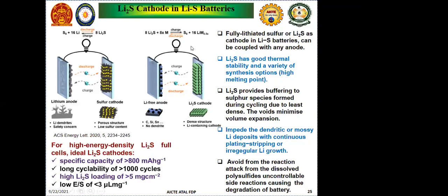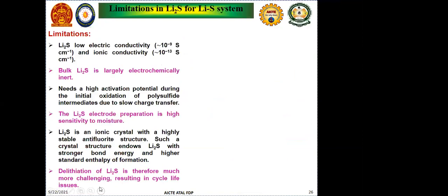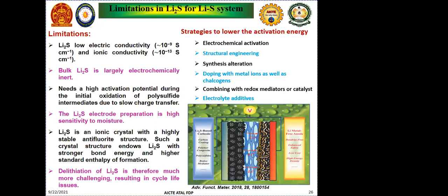We have to adjust the electrolyte as well as electrode material, so that the sulfur loading will be sufficient for the system. Especially for better battery performance, like a specific capacity around 800, and the cycling stability, we want around 1000. So we have to keep a high loading of Li2S, more than 5 mg per cm square for the electrode material, and the best performance is achieved at low E/S, around 3 microliter per mg. So what are the limitations when we use the Li2S system? As we know, the limitations in the Li2S system are low ionic conductivity and electronic conductivity, and bulk Li2S is electrochemically inert.